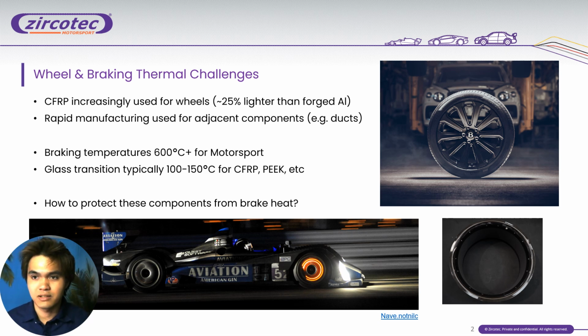For road cars, you'd expect around 100 to 200 degrees, and for motorsport, you'll probably go around 600 plus degrees. But not all of the energy and temperature is transferred to the wheel or to anything like the brake ducts. So you'll probably get, let's say, half of the 600 degrees, which is around 300 degrees, but this is still way over the limit of the plastics inside the wheel, or the actual wheel itself.